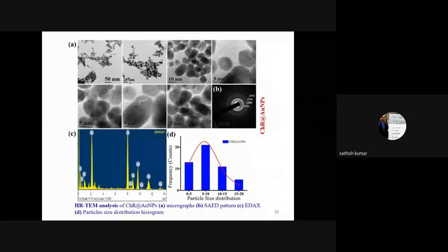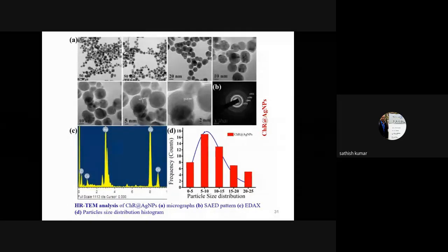So here you can compare both the plant mediated nanomaterials as well as the nanomaterials that have been synthesized using the polyphenol. As in my earlier slide, I have shown 3-4 plant mediated nanomaterials, and those nanomaterials are largely aggregated, but here you can see individual nanoparticles without any aggregation. Here you can see the overlapping of the particles, but this is due to overlapping, not that the particles are aggregated. We cannot say these particles are aggregated. The particles are highly stable without any aggregation.